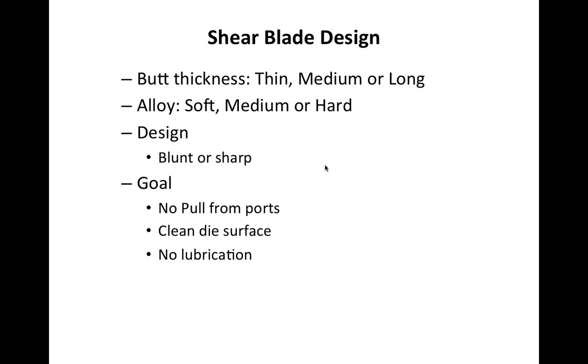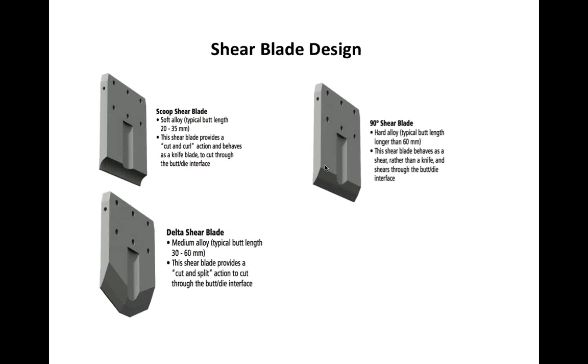What we want to do is have a clear cut and a complete cut on the die face without pulling any aluminum whatsoever from the ports. If we pull alloy out of the ports and we have air gaps in these, the next billet that comes in will create blisters in these areas. And typically, when your butt shear isn't working well, people are also adding a lot of graphite lubrication. Air plus oil or graphite makes explosions, and again, we lose the structural integrity in our profile. These are just three shapes here. On the top left, we have a scoop, which we can use for relatively thin butts, usually 6000 series alloys. On the right is more of something we'd use for a 7000 or 5000 series alloy, which is relatively blunt.